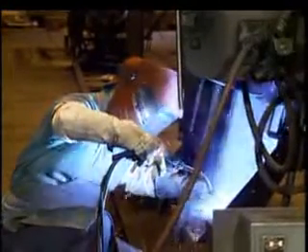The PowerWave power source has waveform control technology. It provides a very fast front edge in the pulse, transferring the droplets quickly. The back edge of the pulse falls at a controlled rate to add the heat input needed to wet the droplet into the puddle. Pulse spray is stable at a wide range of wire feed speeds. The process offers more advantages at both higher and lower wire feed speeds than conventional axial spray. But with the waveform control technology processes, there is much more processing versatility and capability. More choices are available when adjusting the arc length of these processes.